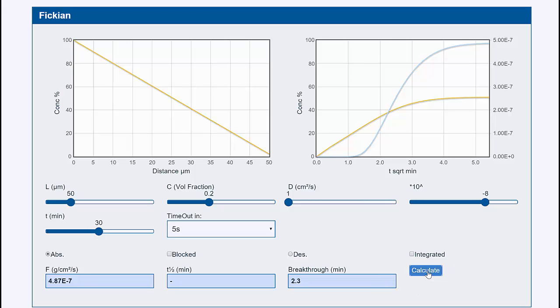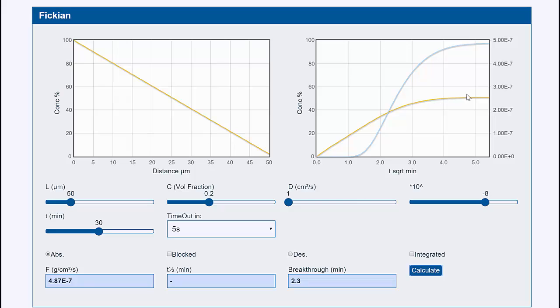When we press the calculate button, we see that after 30 minutes we have this concentration gradient across the barrier. Not surprisingly, it's got essentially 0 on one side and 100% at the other side. The concentration in the barrier itself goes from 0 — because we start off with none in the barrier — up to 50%. So it's half full, because it's 100% full at one side and empty at the other side. That is filling the barrier with material.